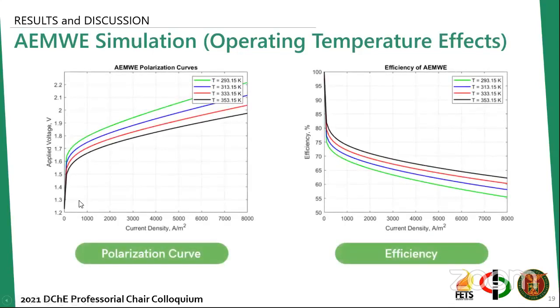For the AEMWE simulation, 5 types of plots were extracted and separated to compare the effect of operating temperatures. The first one here on the left is the polarization curve, which relates current density to the applied voltage. Then we have the efficiency of the AEMWE. From these plots, we can see that increasing the temperature improves the overall performance of the EMWE, given that less voltage is needed to accomplish the same production rate, and efficiency increases.